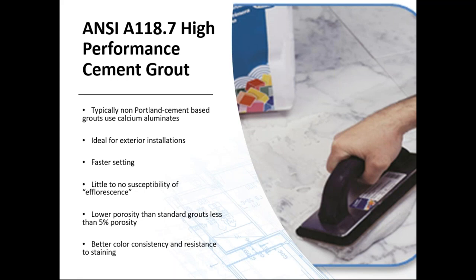These grouts have little to no susceptibility to efflorescence. The free lime that is produced in the curing process of Portland cement isn't coming to the surface, bringing those salts to the surface and leaving that white salty residue known as efflorescence. So if we're looking at a project to try to avoid any of the problems with efflorescence, we go to these types of grouts. They also have a lower porosity, typically less than 5%, which is a great advantage over traditional Portland cement, and which will give you a better color consistency and resistance to staining.